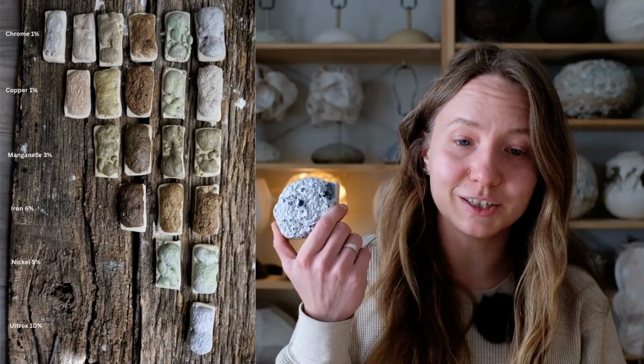I think what I liked is how clearly iron was brown, no matter with which metallic oxide I mixed it with. And then also how Ultrox overruled, but didn't overrule the silicon carbide enough and stayed gray. Although the rest actually changed the color, I believe that silicon carbide is powerful enough. It's very gray and dark, and I added quite a bit of it, so it was actually visible on my textiles here. But even though it was so gray, when I added the metallic oxides, they actually reacted quite well. And I got the whole range of green and brown and orange colors.